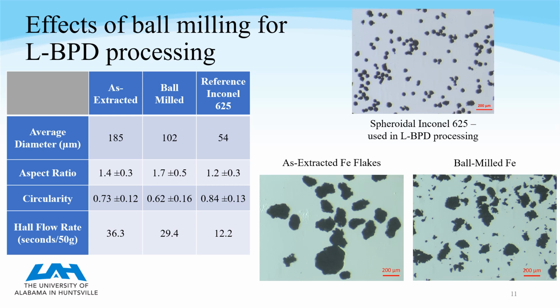Now at the bottom of this table here, we have the Hall flow rate, which is in seconds per 50 grams. That's time per unit mass, which is the inverse of what we would usually think of as a rate. And so when we see that this reference material, the Inconel 625, which does get used in blown powder processing, has a Hall flow rate of 12.2 seconds per 50 grams, when we look over to the ball milled flakes, we see that it's about 2.5 times higher Hall flow rate, which actually means that it's 2.5 times slower. In the same way, the as extracted flakes are about 3 times slower to flow than the reference Inconel. And all that again is because spheroidal powders will flow more readily than flakes.